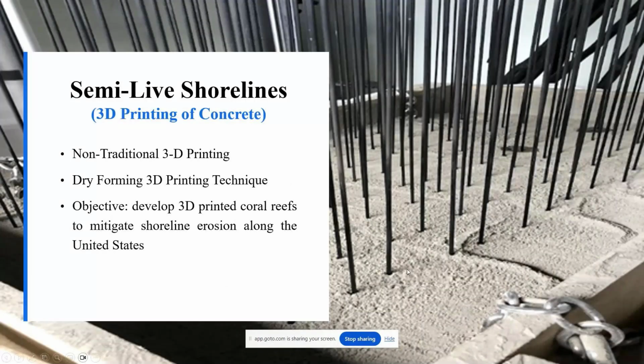Now to the incorporation of our technology, using the 3D printing of concrete to provide a solution for this problem. We have proposed a non-traditional 3D printing technology, which is basically dependent on dry forming, or the use of dry beds, where we have, as you see in the picture, some sort of a container that is loaded with the dry constituents, and that could include cement. It could include any sort of supplementary cementitious material in partial replacement of cement, or as Dr. Taha said in the previous